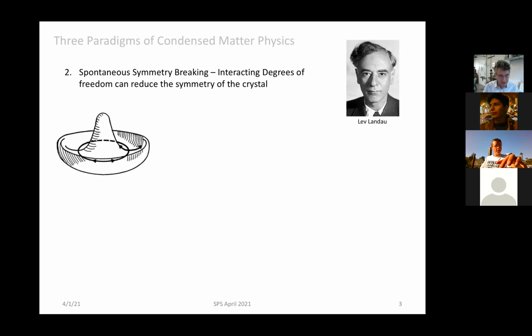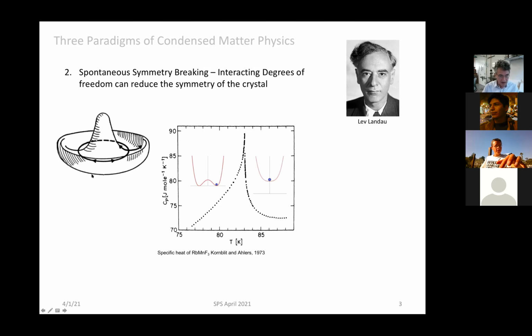A really obvious example, people usually talk about the interactions leading to a potential well that's like a Mexican hat. But the most obvious type of spontaneous symmetry breaking is if you have magnetic atoms and their interaction is not the type that wants to make neighbors point in the same direction, which would lead to ferromagnetism, but they're anti-ferromagnetic. So right away, you've led to a doubling of the unit cell. Before, in the high temperature state, there would be a spin on an atom, and the symmetry of the system would be the symmetry of the lattice. But once you turn on interactions and you can get this up, down form, that breaks the symmetry of the unit cell. That leads to a reduction of symmetry of the crystal as a whole.